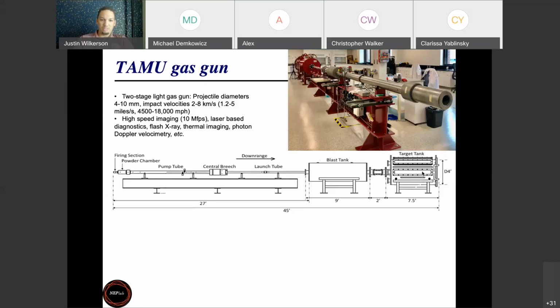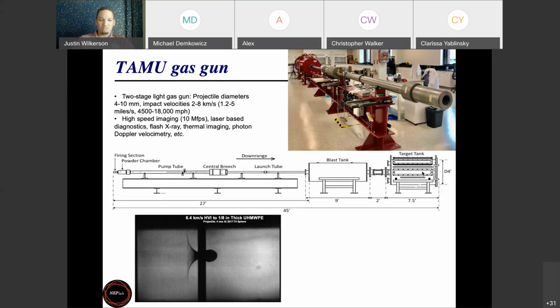I have a couple videos here that will hopefully motivate the talk. Here's a projectile coming in from the left at 6.4 kilometers per second, and it's impacting a 1/8 inch thick, ultra-high molecular weight polyethylene plate. The projectile is a 4 millimeter aluminum alloy sphere. You can see all the impact damage that's generated. We have both front face debris and back face debris. The projectile penetrates through this target, obviously.